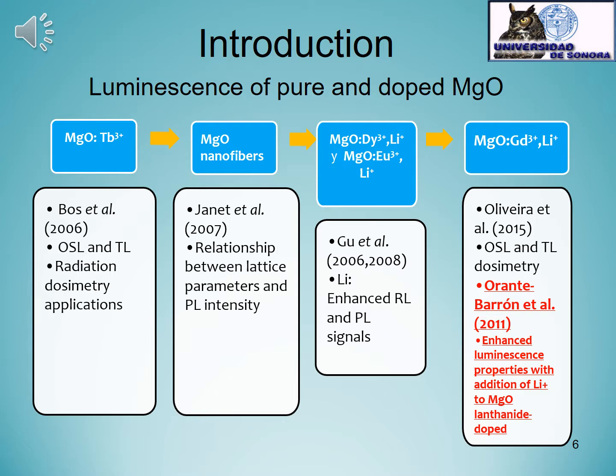And we observed that we could make a kind of tuning of the thermoluminescence signal and the radioluminescence signal according to the dopant, and also to the molar ratio of the oxidizer and the fuel, which is the reducing agent, as I mentioned before.